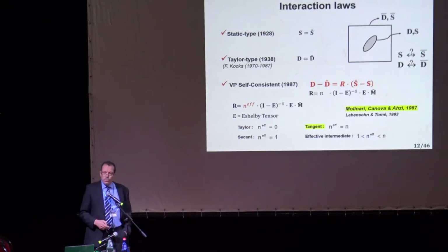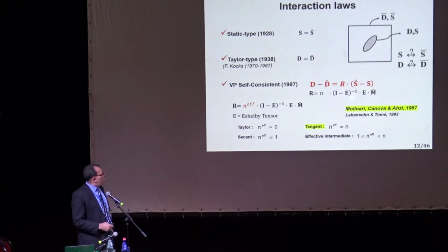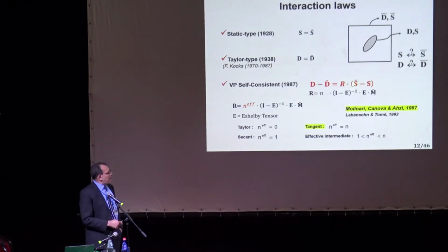We can make use of the Eshelby tensor, okay? Or go through solving the equilibrium equation, use integral equations, and solve. And then at the end, we end up with this relationship here. This is how D, the local strain rate, relates to the macroscopic strain rate. So the difference in strain rates is related to the difference in stresses. Sorry, this should be S bar. There is a mistake here. And this R here we call the interaction tensor.